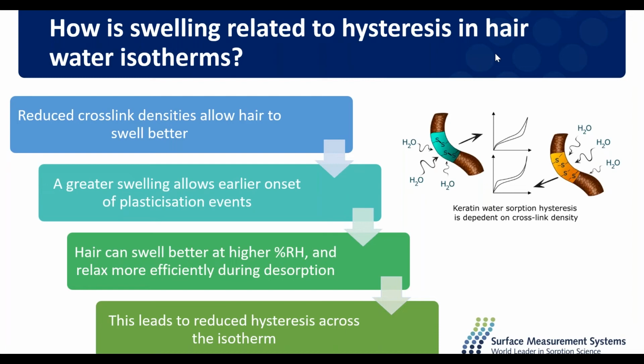And so, yes, from this experimental work, we think that swelling and crosslink density have a very strong link to the hysteresis in hair. But clearly, there's always more to investigate with more experiments and potentially a future model.